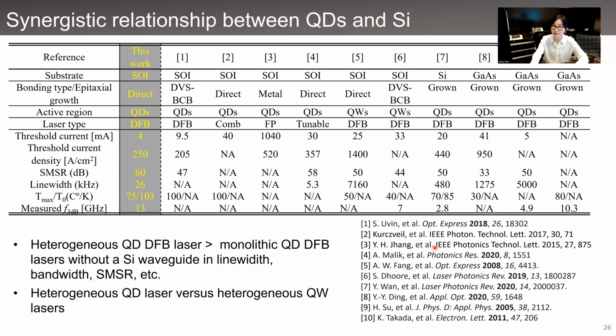So this table compares the device performance of this work and the previously reported work. Again, this table clearly shows that the heterogeneous quantum dot DFB laser with the silicon waveguide can significantly outperform the monolithic quantum dot DFB laser without a silicon waveguide in terms of linewidth, bandwidth, thermal rollover, etc. Which we are very excited about, since when you put lasers on silicon, you not only get a better substrate, you also get better lasers.